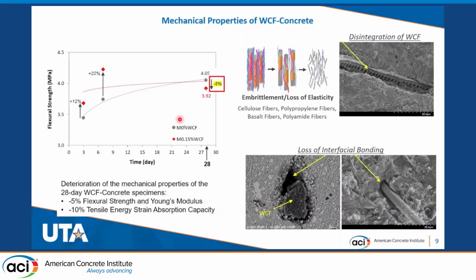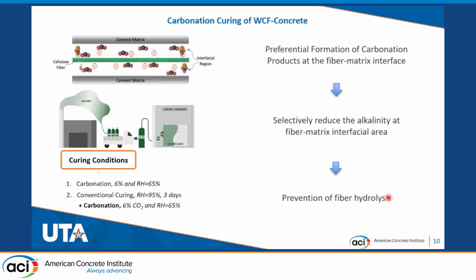This phenomenon is not really specific for this type of cellulose fibers. We see this often in other types of fibers, such as the polypropylene fibers and the basalt fibers. So, to alleviate this problem, our target is to protect the fibers from being attacked while in the high pH of concrete. So, we need to prevent the fibers from hydrolysis. In this research, we applied a novel technique that would selectively reduce the alkalinity at the interface between the fiber and the matrix, and we applied some carbonation regimes that I will explain in the next slides.